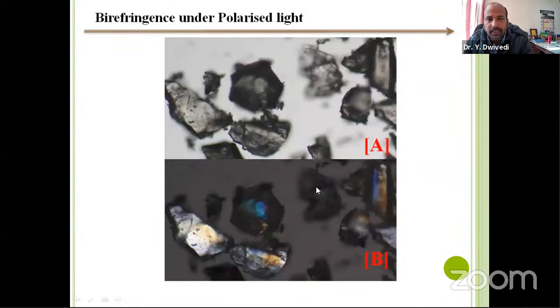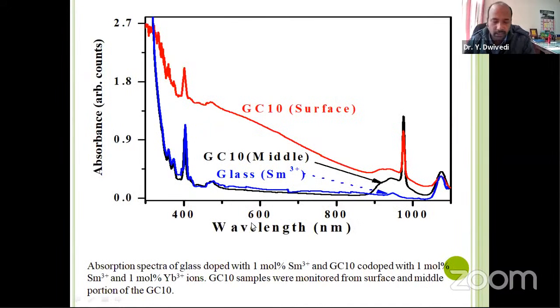We also see how polarized light actually affects this, so you can make some calculation for crystal growth in glass. Here in this case, you can see simple glass particles. Under polarized light, you can see some colors - blue, red, and yellow - which shows the stress inside the crystal and formation of these micro/nanocrystallines in the system.